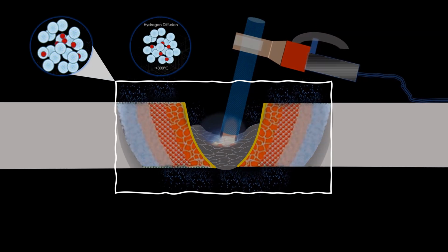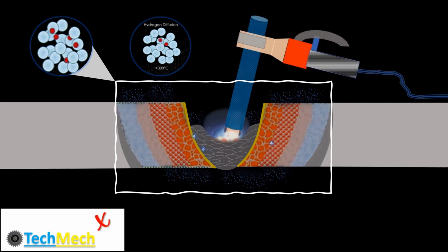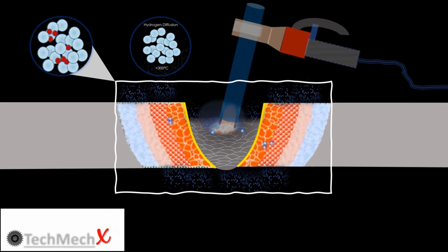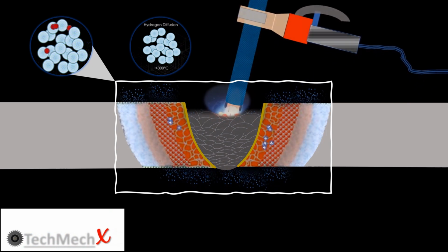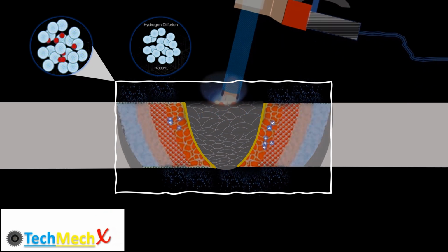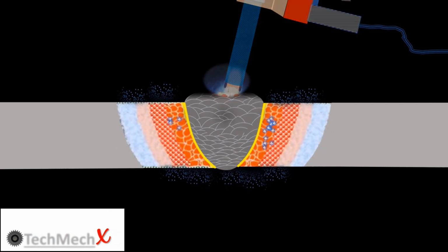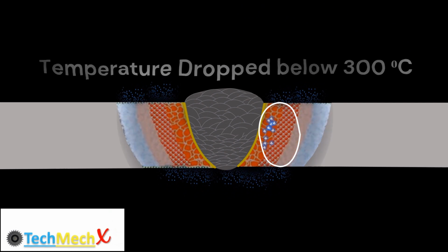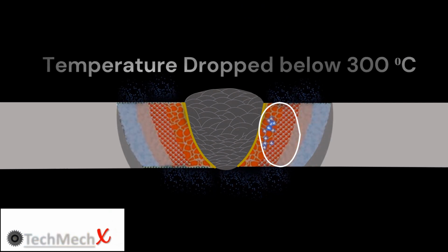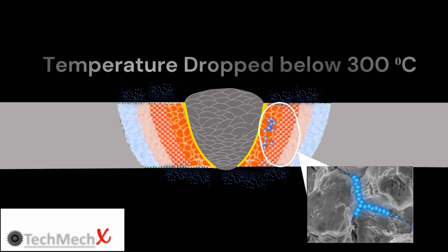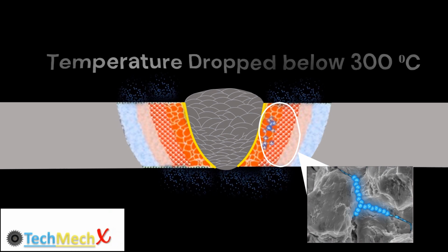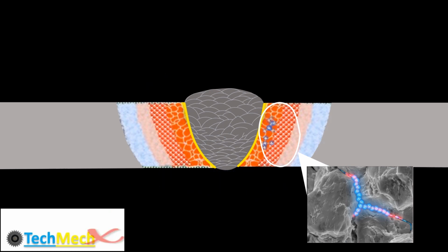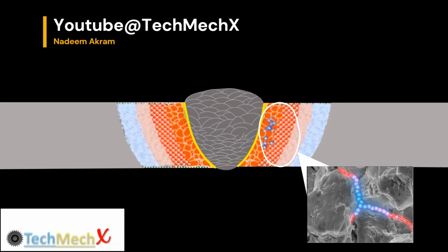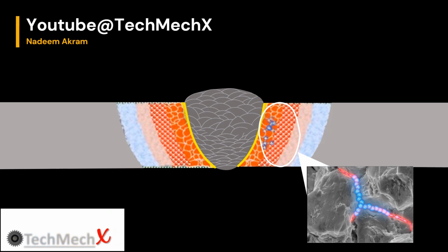Once welding is completed and the metal solidifies, hydrogen atoms continue to diffuse outwards and escape into the atmosphere until the weldment cools. However, as the weldment cools down to ambient temperature, below 300 degrees centigrade, hydrogen diffusion slows down significantly. This leads to the trapping of hydrogen, typically within the heat affected zone. Under specific conditions such as a susceptible microstructure with high hardness and a brittle nature, along with high tensile stresses, these trapped hydrogen atoms can trigger hydrogen-induced cracking.